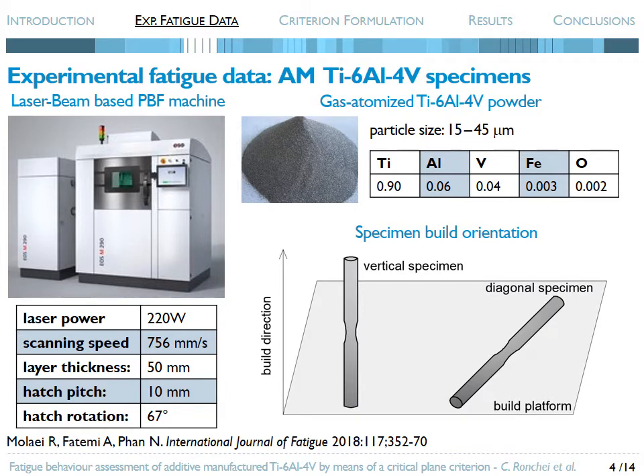In particular, the fatigue tests examined are related to an experimental campaign recently performed by Molaei and co-workers on specimens made of AM titanium alloy Ti-6Al-4V. Such specimens were produced by using a laser beam-based powder bed fusion machine with the fabrication process parameters listed in the table on the bottom.